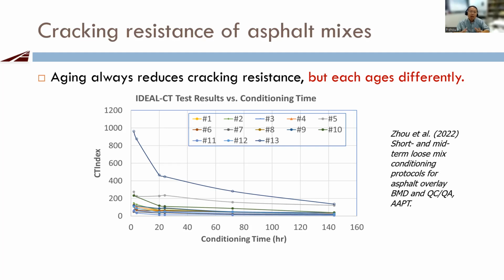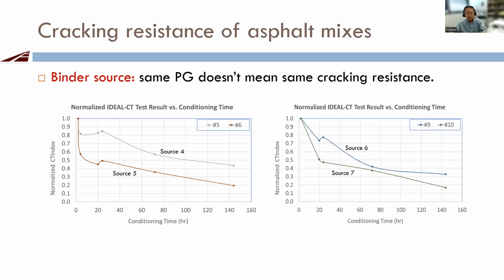I'm sorry, some of the mixes have the same gradation, exactly the same gradation, same asphalt content. The only difference is binder type. The same PG, even the same PG. You're going to see again, different mixes age completely differently. And the binder source, again, these two mixes have the same PG and same asphalt content, same gradation, same aggregate, only a different source.